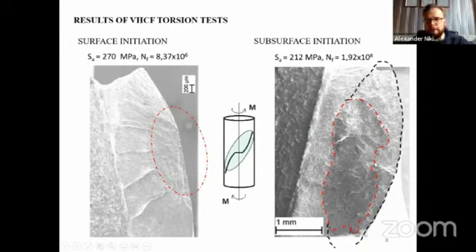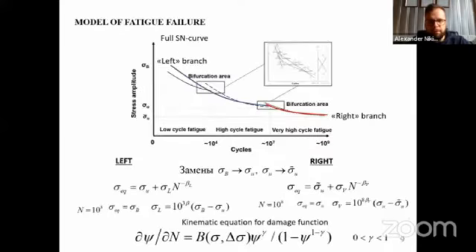In this case, we have two cracks, one developing in a plane of one orientation and the second one perpendicularly, starting from the surface. When we have subsurface crack initiation, we usually observe the X type of cracks. In order to better understand this phenomenon, we tried to apply numerical simulation and model the crack with different crack initiation sites. Here are some details about the models that we use.